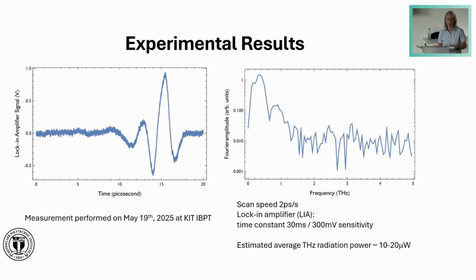In this sense, we focused on setting up the experiments, which took us a couple of days, and finding the best arrangement. Then on searching for the signal, which also took us a couple of days. And when we found the signal, we focused on optimizing the parameters for the lock-in detection, and also the scanning speed. But we see we have a very low intensity in the terahertz radiation beam. My estimate is 10, 20 microwatts, which produces about 10 volt per meter fields.